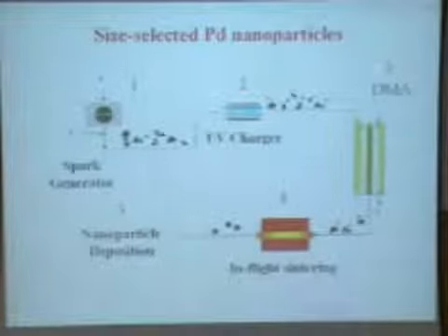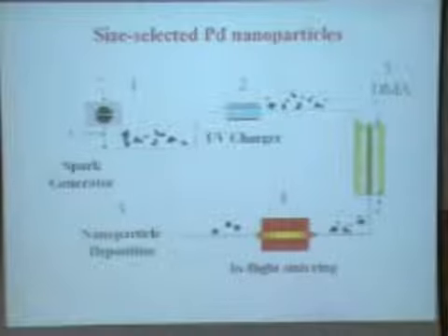This is the method which we are using to make size-selected nanoparticles. It's a very interesting method. It has, in fact, three or four steps. In the first step, it's a spark generator method. It's called a spark generator. We just want to evaporate the material. We have palladium in bulk form, wires or rods of palladium. Between the two rods of palladium, there's a spark generator. The spark erodes the palladium metal, and the palladium atoms go into the vapor phase. It's some sort of heating or sputtering process.